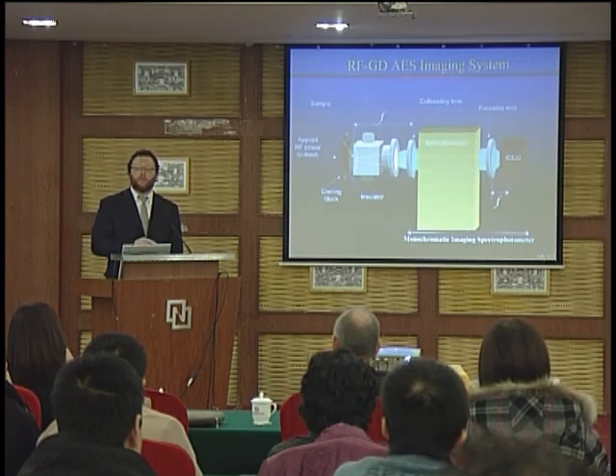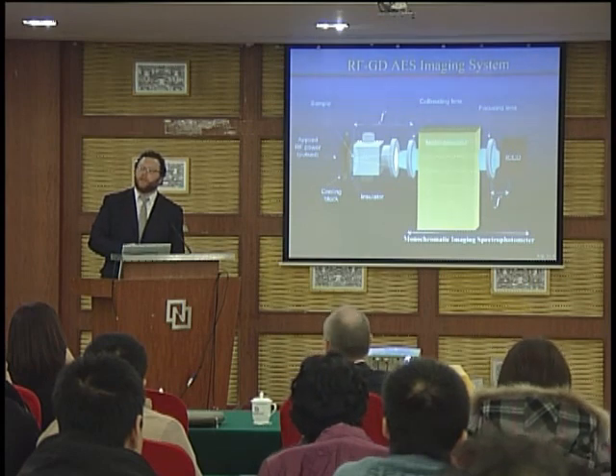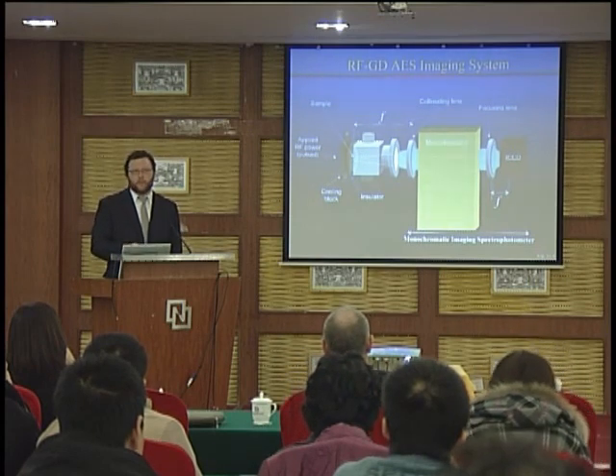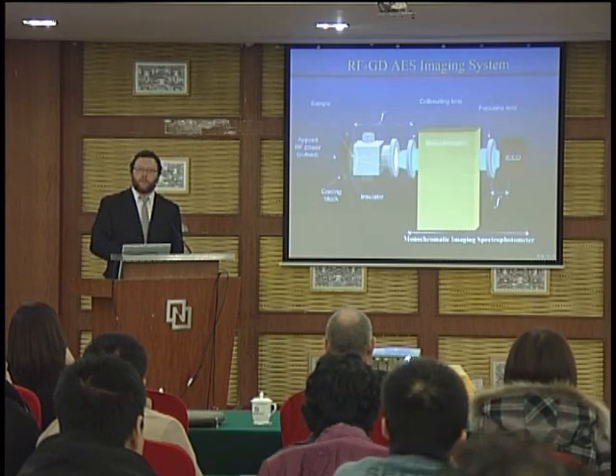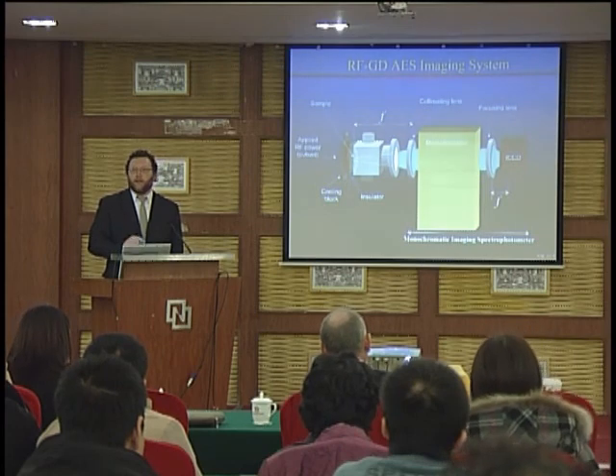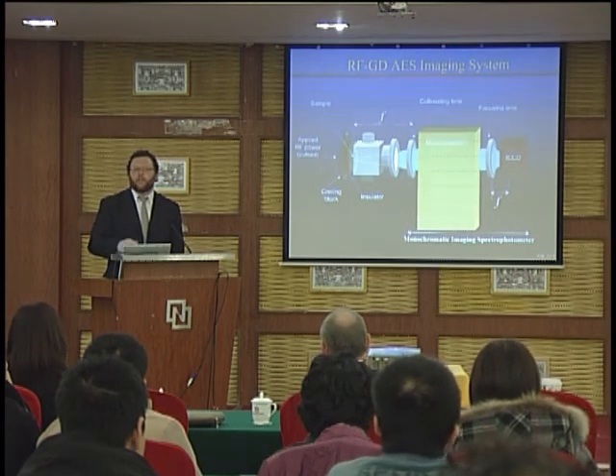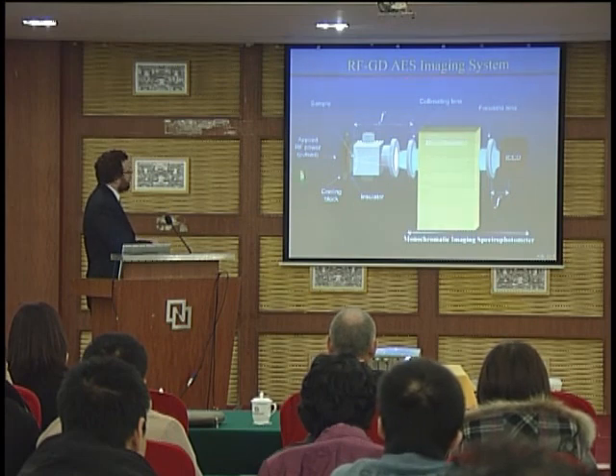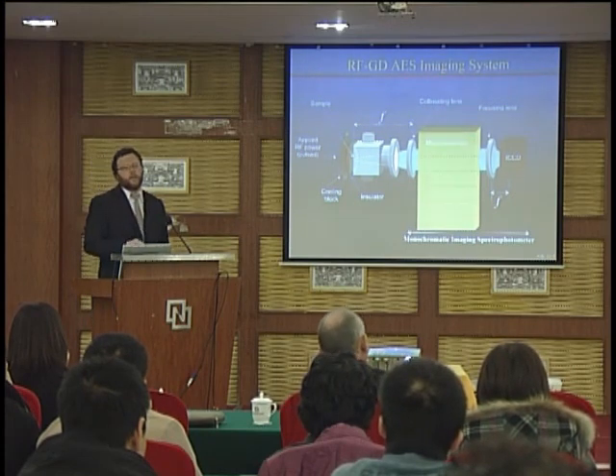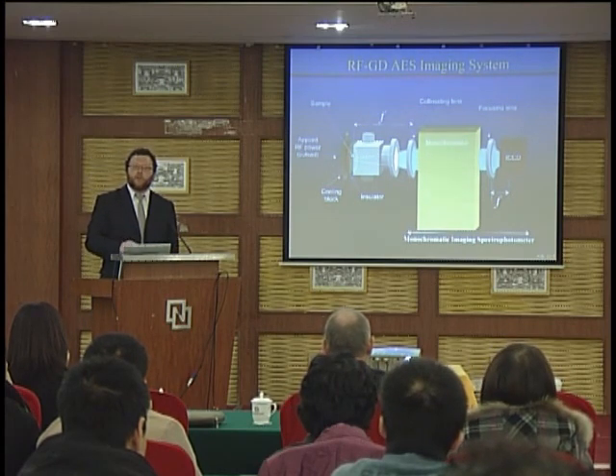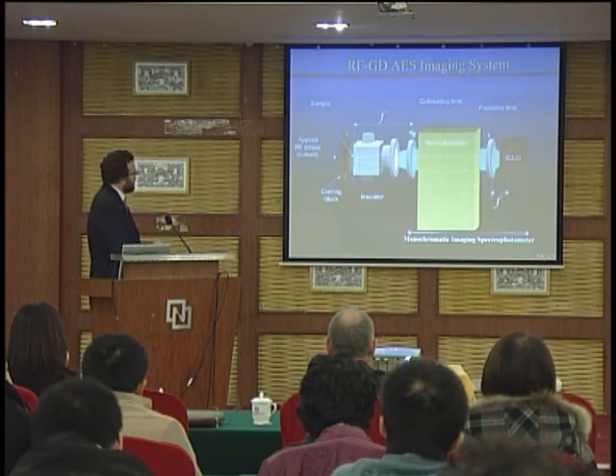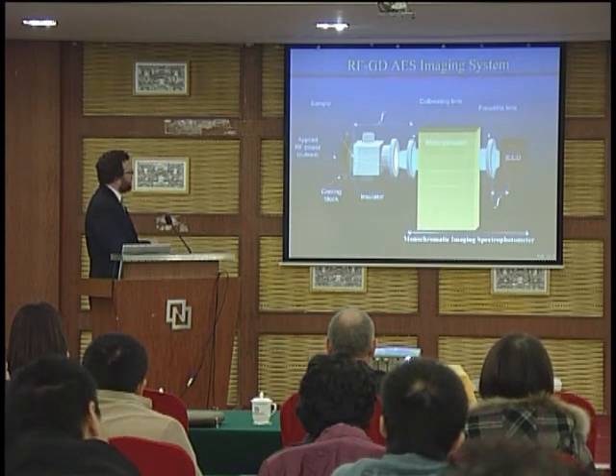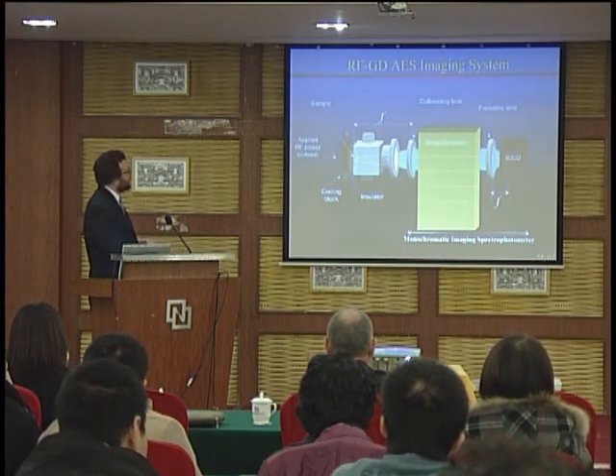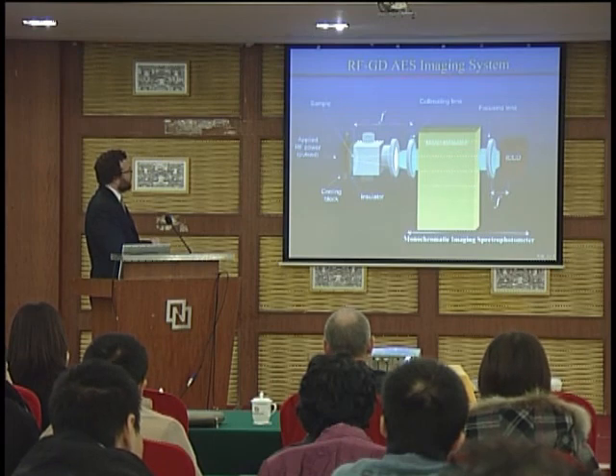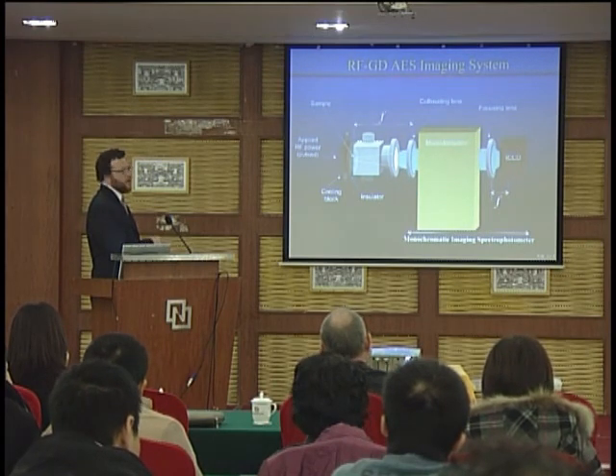And we do it by using something that we call a monochromatic imaging spectrophotometer. It's basically just the same type of instrumentation system that you typically use, but we tweak it in just a slight way. So here's a very typical glow discharge cell, again in a reduced pressure of argon as the environment. We collect the emission from the sample cathode, which sits here, but instead of placing the lens at 2F, we place it at F.